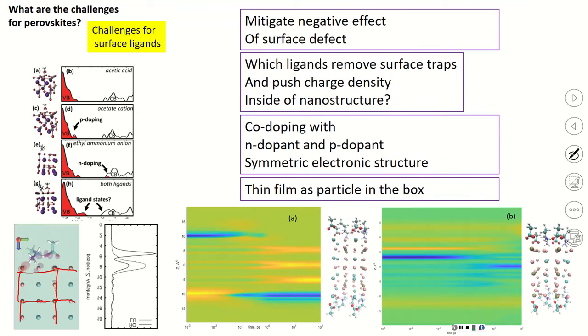We need to bring here Daniel for the exact initial state for this excitation. But it is expected that there will be a progression of the degenerate states of this localized of holes, top and bottom. But in numerical treatment, nothing stays degenerate. Degeneracy is always broken. So spontaneous break of symmetry by some little corruption of geometry. So there is a lift of degeneracy, and definitely one will be a little lower and another a little higher. Therefore, we do not see equal splitting.